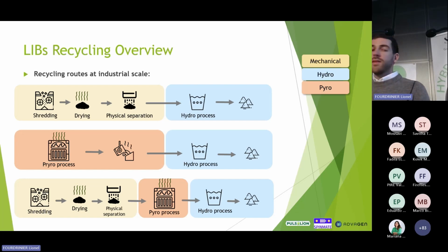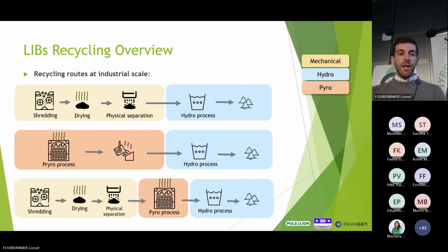And in the hydrometallurgical process, there is one first step, which is the leaching. So in the leaching, the valuable metals from the black mass, from the solid matrix, are extracted into a liquid phase, into a liquid solution. And then from this liquid solution, we can selectively recover the target metals. There are different techniques for the selective recovery, like solvent extraction or selective precipitation. But at the end of the process, if you are recycling, for instance, NMC, you will have the salts of the metal. So you will have nickel sulfate, cobalt sulfate, lithium carbonate, and so on. And you can use these materials to produce new cathode materials.